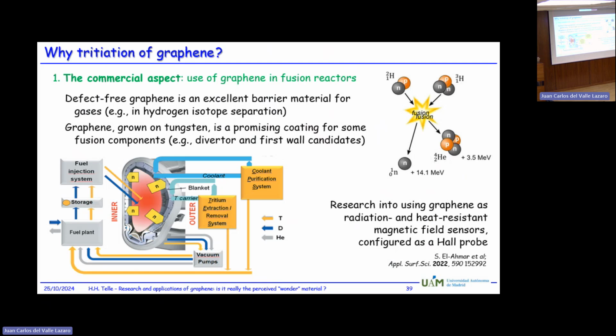So everything is recycled. So in the recycling, you actually have in the gas now a mixture of deuterium, tritium, but also DT, which is actually the mixed isotope molecule. So you have to separate them again for the injection of pure deuterium and pure tritium. And that is actually done with isotope separation units, where nowadays membranes of graphene are used, which assist quite strongly, sort of catalyze, the separation of these isotopes. So this is one application.